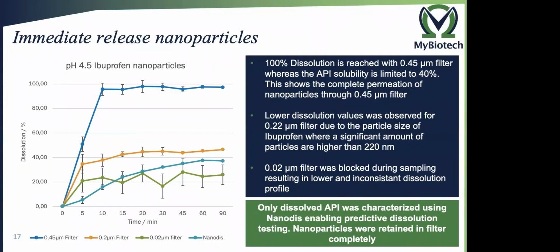On the left side, you can see our dissolution results. When we use a 0.45 micrometer filter after we take the samples, we end up seeing 100% dissolution within 10 minutes, which is not surprising because all the particles are smaller than 450 nanometers, so they all go through the filter and at the end are analyzed together with the HPLC. When I use a 0.2 micrometer filter, we adjusted the particle size of these nanoparticles to an average of approximately 200 nanometers, so that I can filtrate some of the particles, but some of the particles are still in the dissolution medium, so that is why I see a lower dissolution profile.